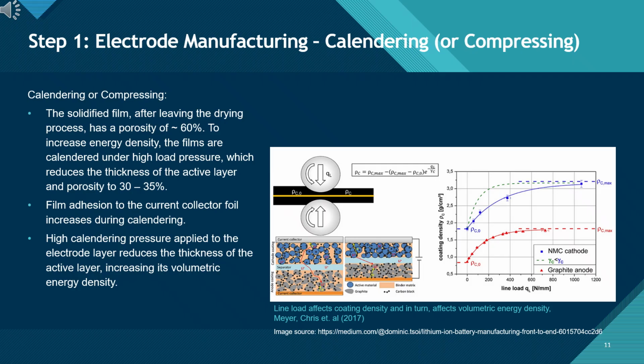Calendering also improves the adhesion between the electrode coating and the current collector foil, making the film stronger and less likely to peel or crack during later processes. The graph below illustrates the effect of line load on coating density. As roller pressure increases, both cathode and anode density rise until they reach a maximum limit. The balance is important. Too little pressure and the electrode stays weak, too much and it can lose flexibility or crack. In short, calendering is about finding the right pressure to produce electrodes that are dense, durable, and energy efficient.